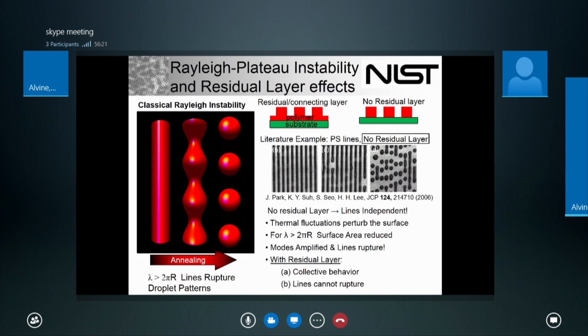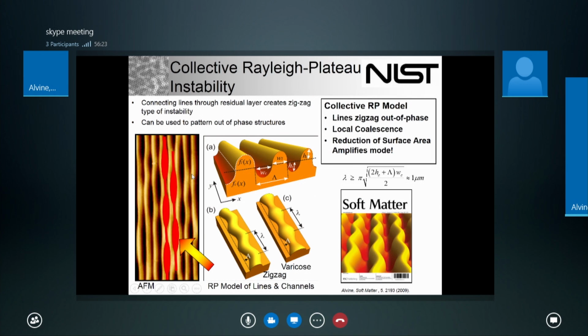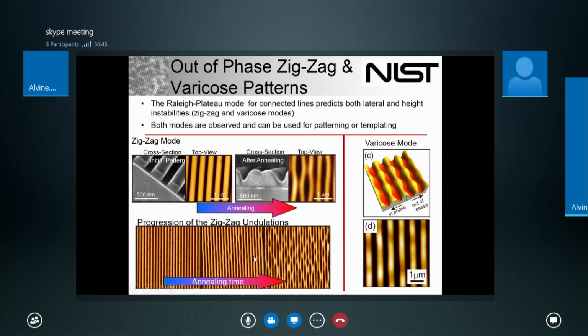What happens there, in some cases, is you get essentially a collective instability. You'll get lines forming what looks like a zigzag pattern, or they're all undulating. This is just another flavor of the Rayleigh-Plateau instability, where the surface is trying to decrease its surface area, and so you get this varicose mode and the inverse of the varicose mode, which is the zigzag instability. You can use that to pattern the structure, and you can potentially make things that are more complex that can be useful for nanoplasmonics.